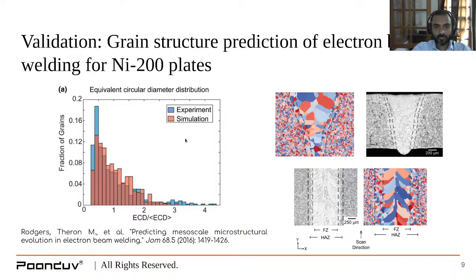And if we talk about experiment and simulation results, visually it's all good, but if you were to compare quantitatively the experimental data with simulation data, you can see the ECD, which is equivalent circular diameter. What they have done is convert the circumference of a single grain into a circle, so that they have some relatively same parameter to compare against. And for the fraction of grains, for example at an ECD of 1, you can see experiment and simulation have a very similar fraction of grains. There are some variations, but nevertheless I would say that these are quite promising values